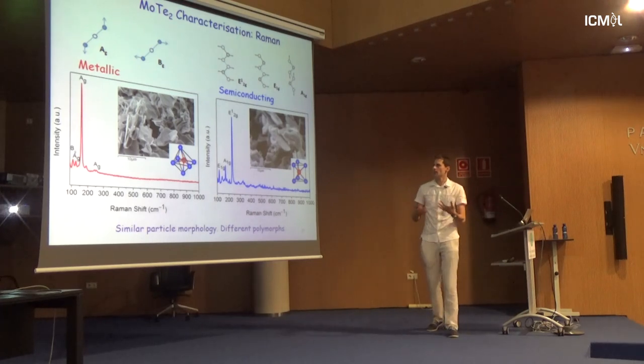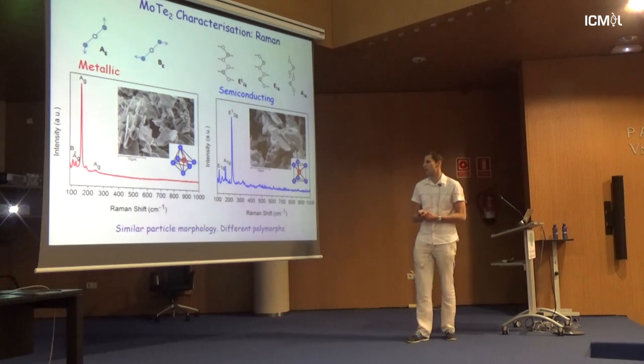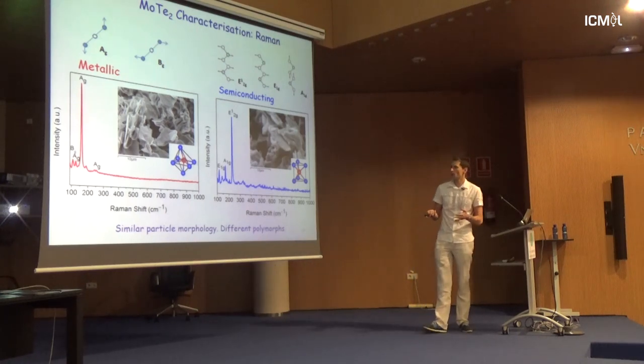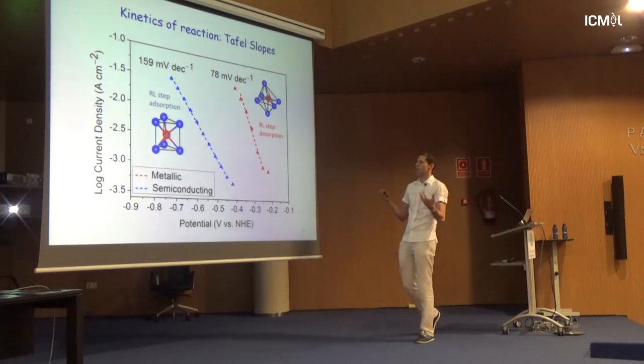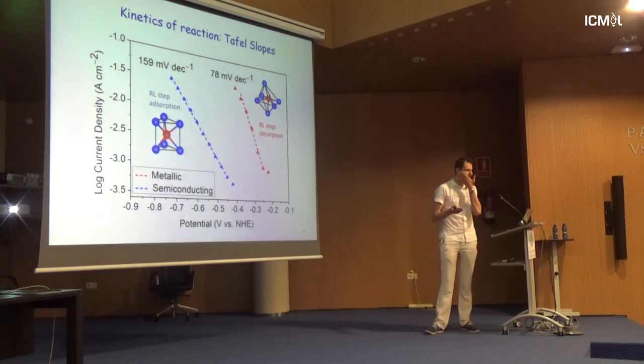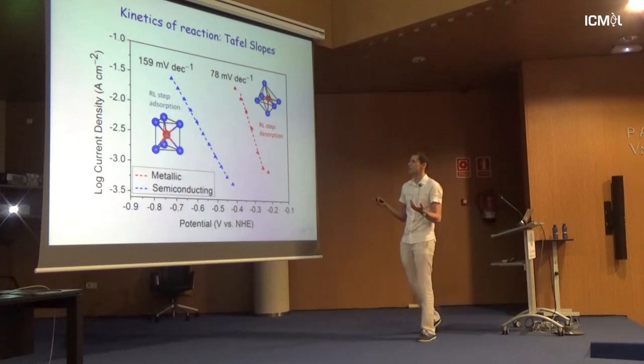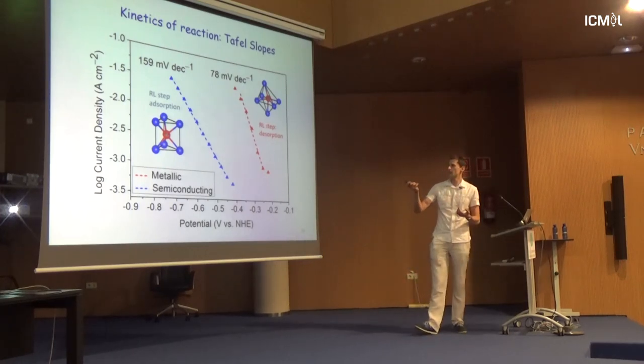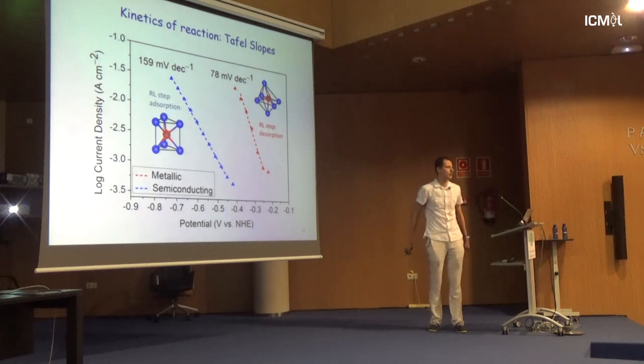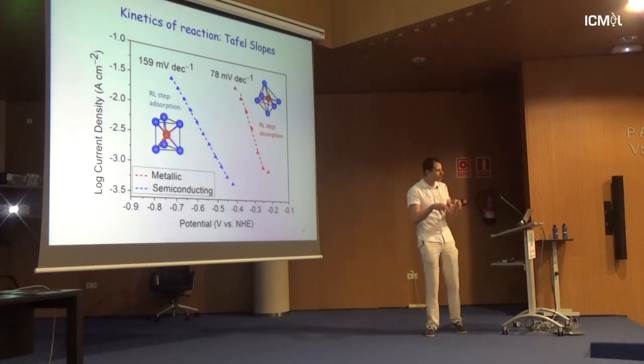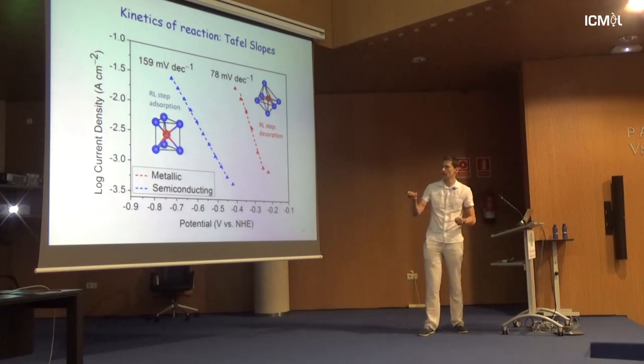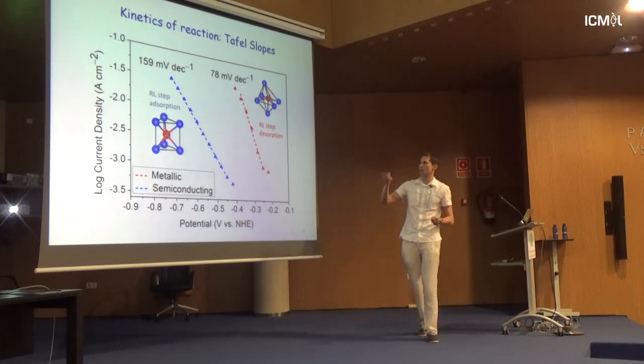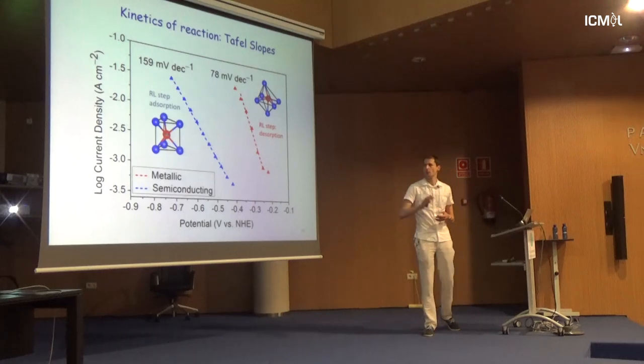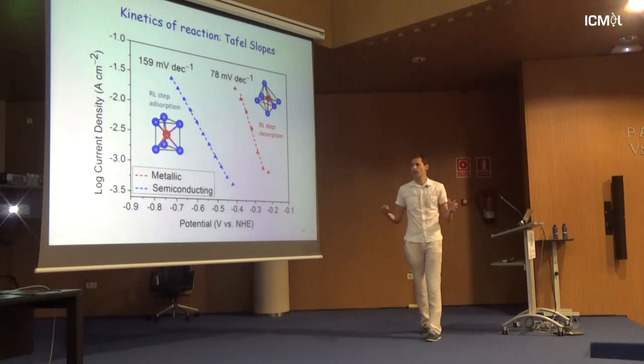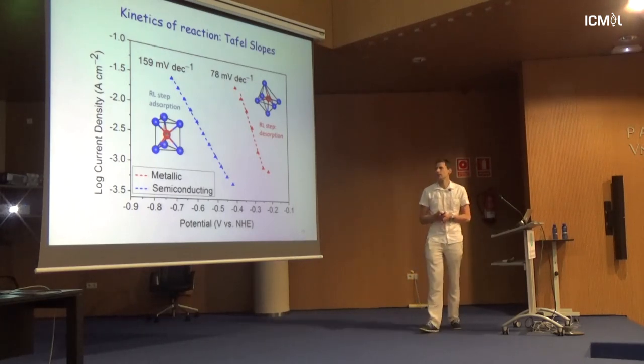So we try literally not to manipulate. So similar particle morphology, different polymorphs. Okay? And then they show completely different kinetics of reaction. So here the rate limiting step is desorption of hydrogen, so it wants to stick to the surface. While in this case, it's the adsorption, so it doesn't stick to the electrode. So they're very, very principally different materials.